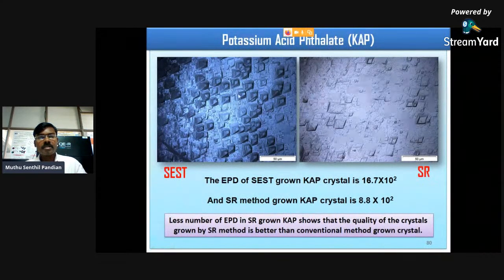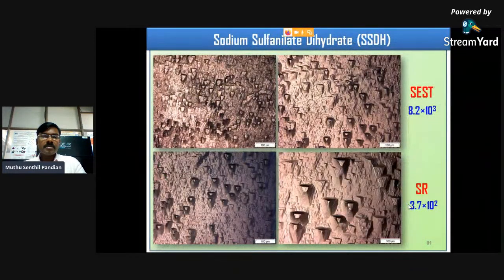So this is the low soluble KAP single crystal. This is for conventional method grown crystal. This is for SR method grown crystal. For conventional method, 16.7 × 10^2 cm^-2. But in the case of SR grown crystal, it is half, 8.8 × 10^2. So these are the sodium sulfanilate dihydrate single crystals. This is for conventional method and this is for SR method.